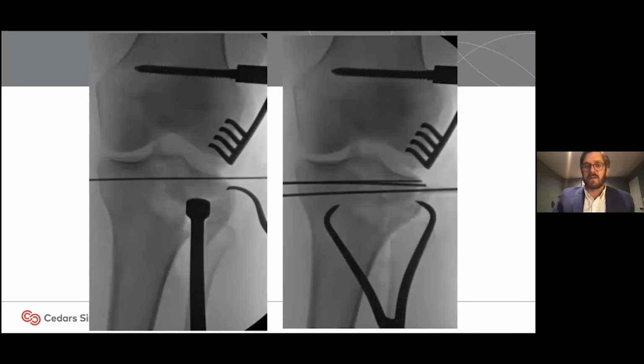We elevate the articular surface, we reduce it and hold it. And at this point, we need to decide how we want to fill that gap. In this case, we have a moderately sized defect. This defect is closed. We have really great cortical reads and reduction and no comminution. And again, we're looking for compressive strength.